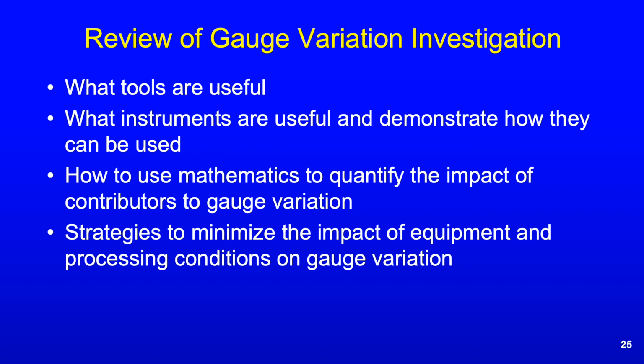The Fourier series analysis is useful to identify contributions to gauge variation in equal repeats around the bubble, and you can use that to start working on, okay, what am I going to try to fix first? I also mentioned that looking at extruder temperature profiles is an important tool to improve both quality and output and workarounds when you have severe problems. And just one last point. When I walk into a factory and I see that the same temperature profile is used on all the extrusion lines, I conclude that they're letting the extruder be the boss, not the